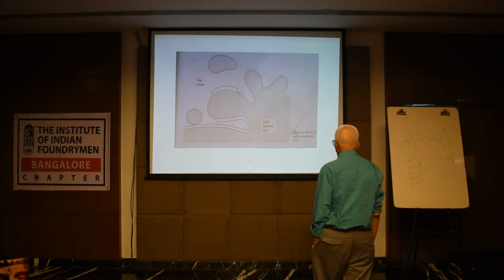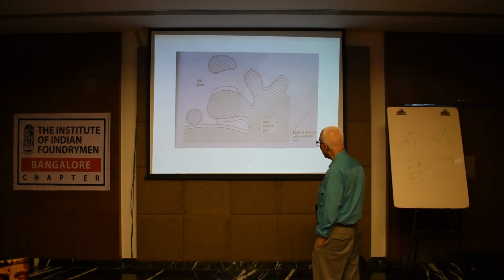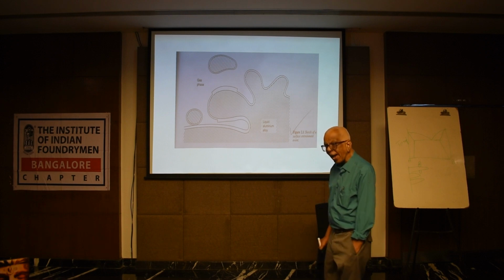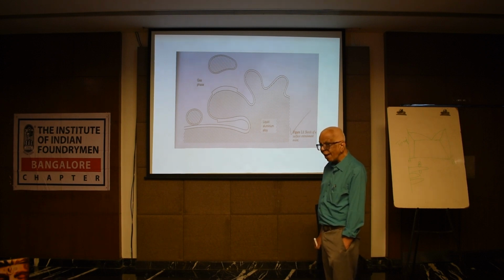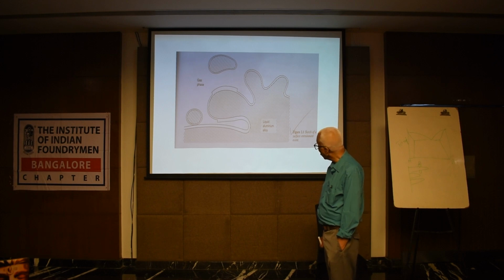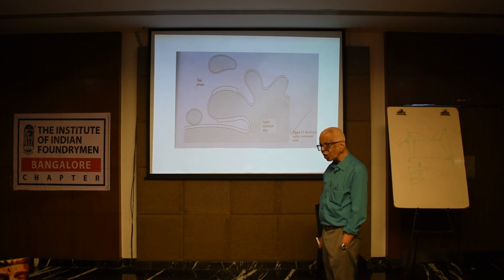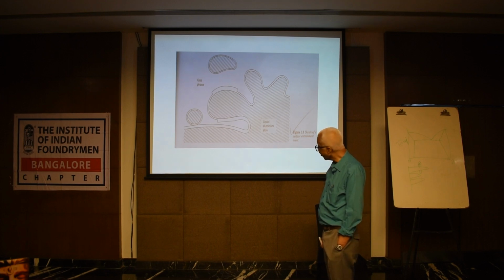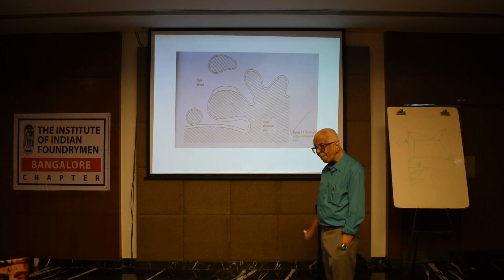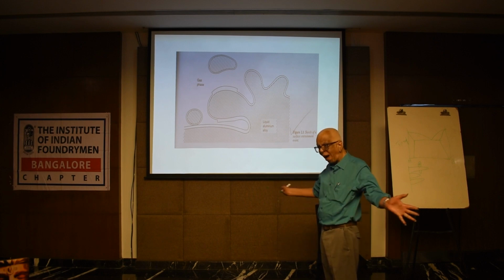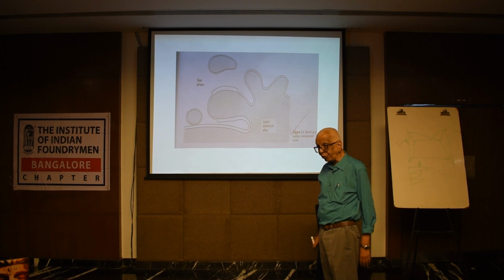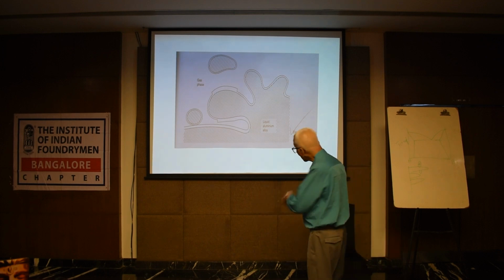Now we get back to entrainment and how air or gas gets entrapped in a bifilm. You can see the entrapment in aluminum alloy, for example. It's susceptible to hydrogen dissolution. So the hydrogen gets entrapped in the bifilm, and when the bifilm unfurls, there is hydrogen porosity, which deteriorates all the properties. That's a landmark.